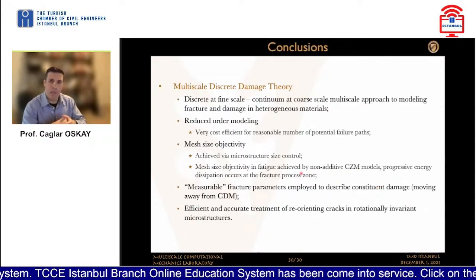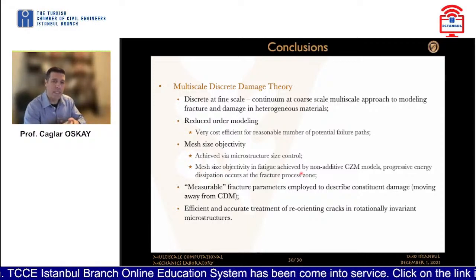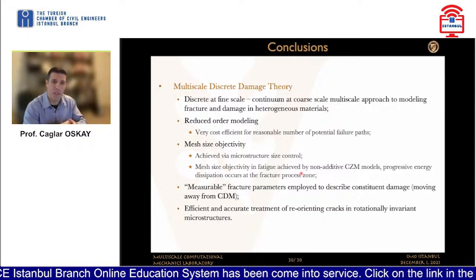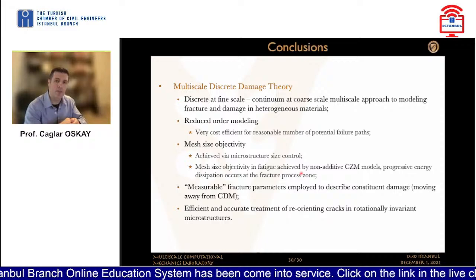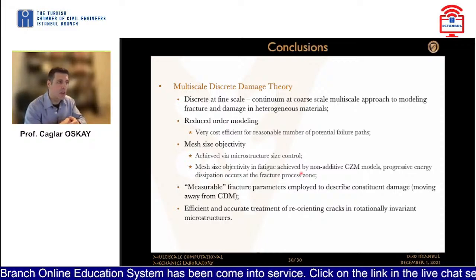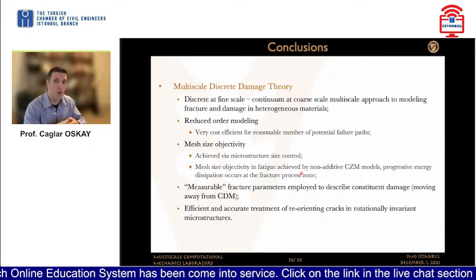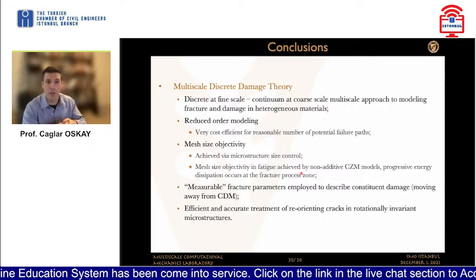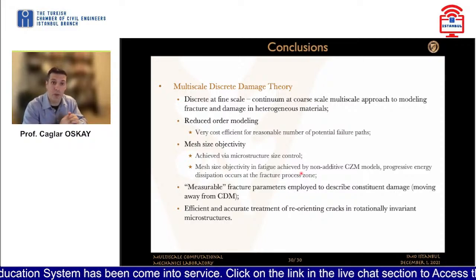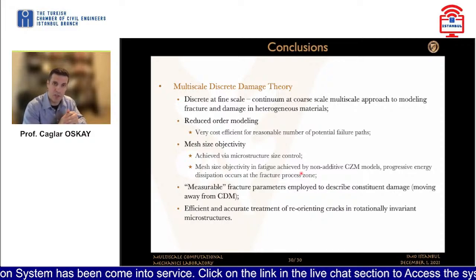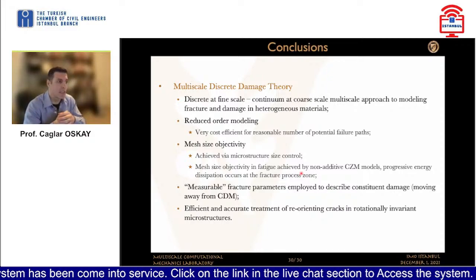With that, I would like to conclude. So we have established a multiscale discrete damage theory that can capture the failure behavior quite accurately for both static and fatigue loading conditions. It incorporates the material microstructure into structural simulations. This is a novel approach in that sense.